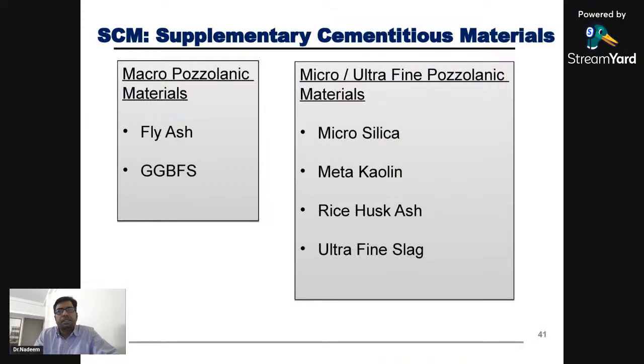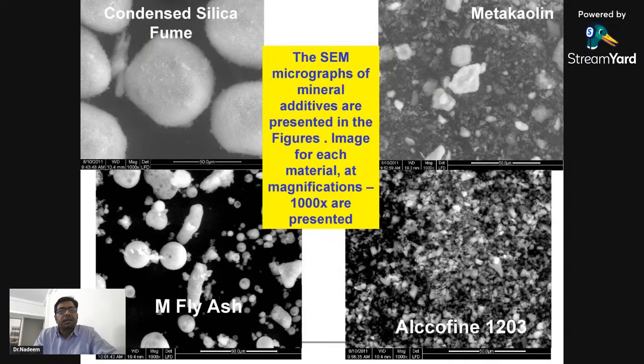So these are the supplementary cementitious materials. So at a macro level, pozzolanic materials are fly ash and GGBS. At a microfine level, we have microsilica, metakaolin, rice husk, or ultrafine slag. We have one product, alcofine. If you just see the SEM micrographs of those materials, so left side if you see condensed silica fume, this is metakaolin, this is alcofine 1203, and this is microfine fly ash. So these are the microfine products being used in concrete.